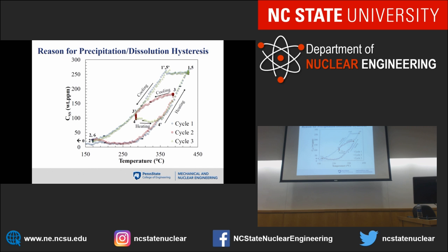Here's another point. The reason for the hysteresis is this. He thought, well, what would happen if I didn't dissolve everything and I started cooling, right? So I go up here, I dissolve everything, I precipitate, I follow the precipitation curve. I go up to 3, I don't dissolve everything, and I start cooling. I start precipitating immediately. Instead of having a flat curve here until I hit the precipitation curve, like what I see at the top here, I will start going down immediately, which means that when the hydrides are present, precipitation happens immediately. Precipitation by growth of the existing hydrides, not nucleation of new ones. Okay? So this is a nucleation limit, and here what we have is precipitation by growth. And here he's just showing the same effect: if I hold the temperature, it keeps going down because I keep growing, etc.